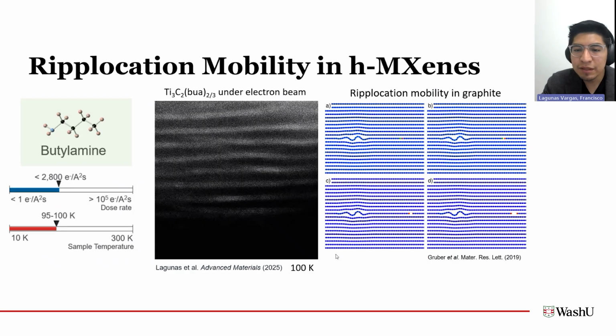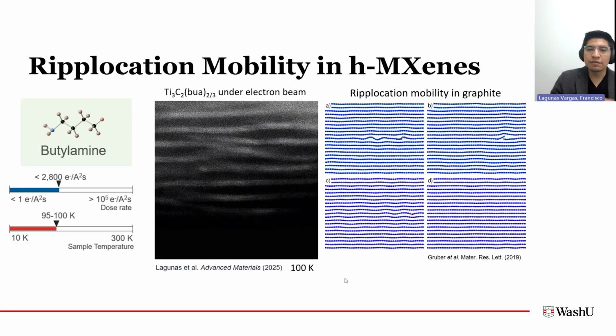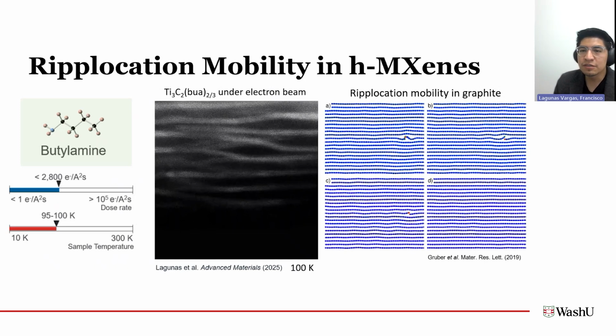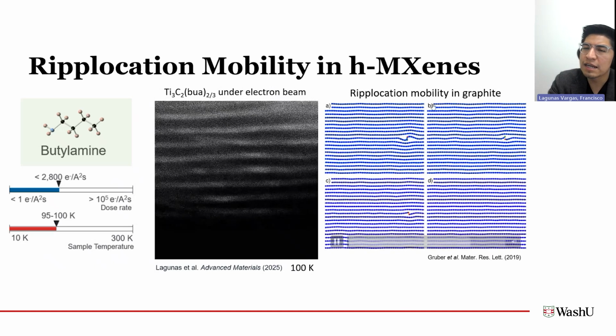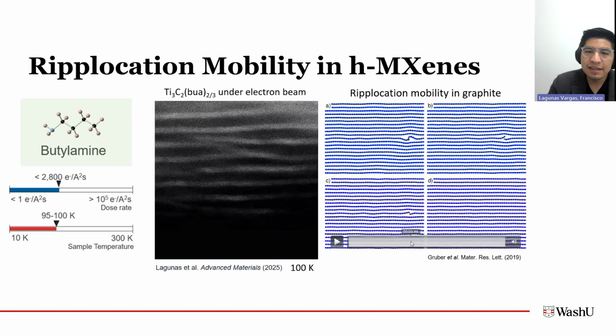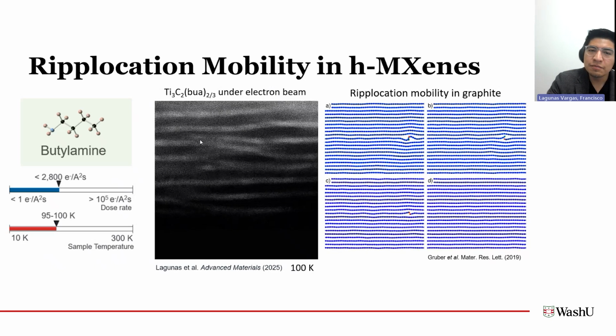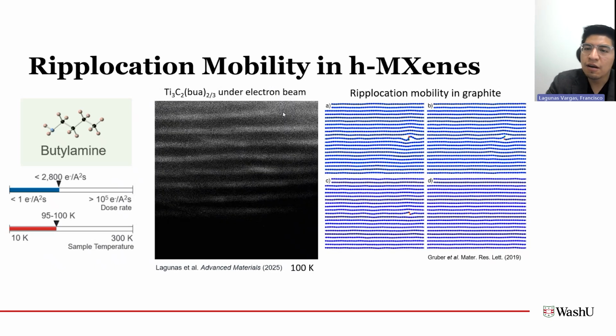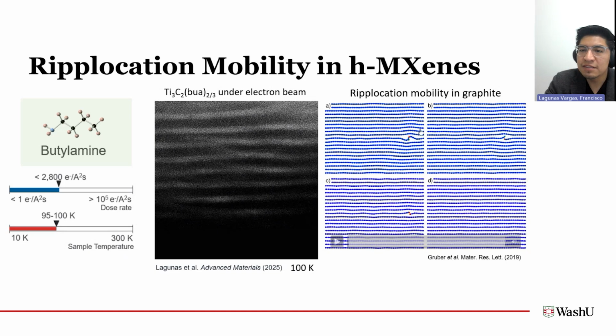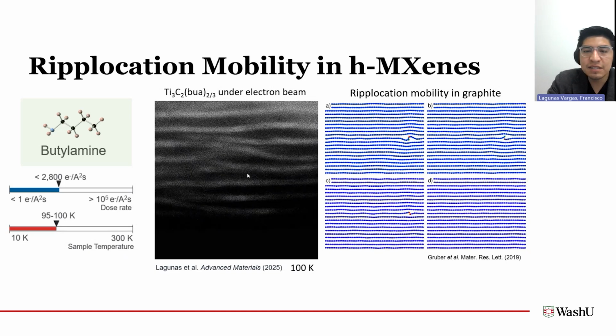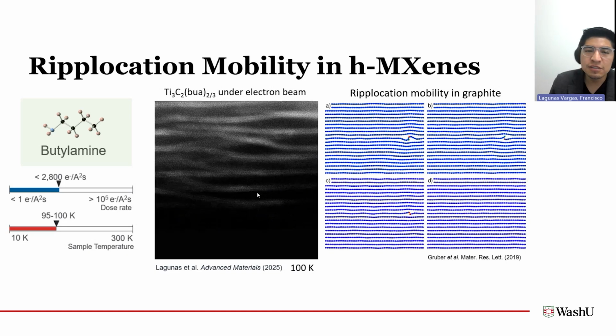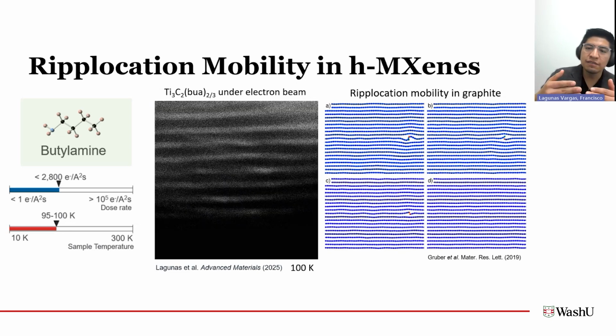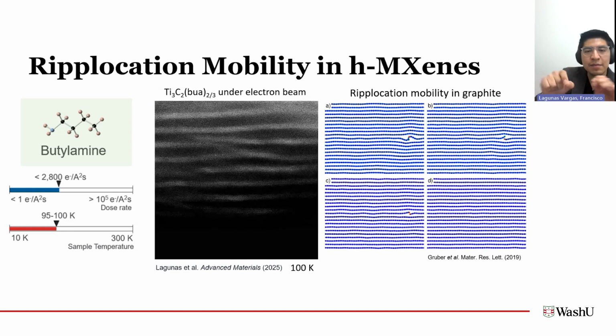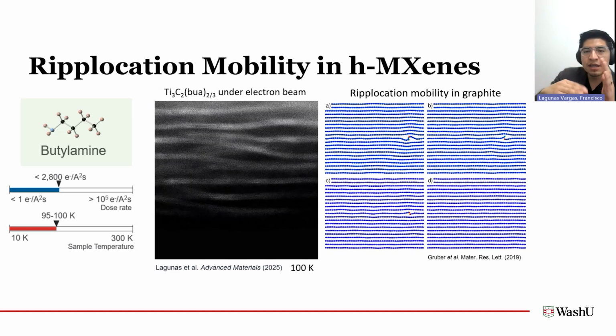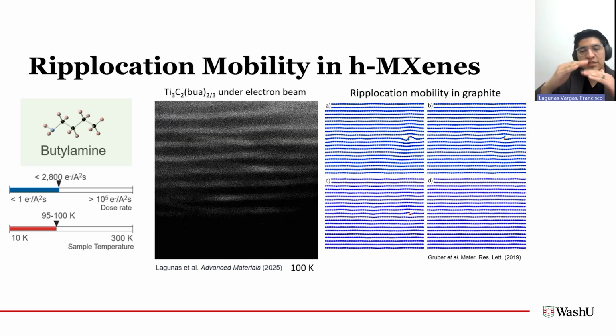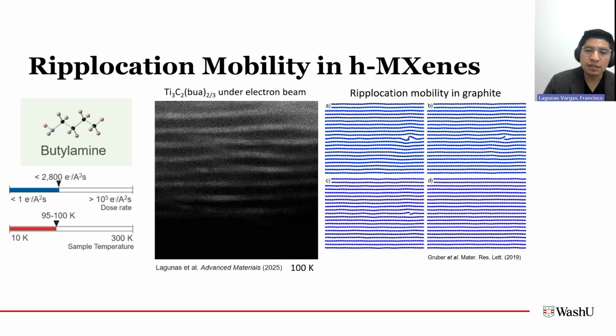So there's a lot of work where people have done computational modeling of the motion of these Ripplocations in 2D materials. Here's one where a group did a molecular dynamics simulation of Ripplocations in graphite. And you can see the movements that they observe tend to match what we see. You can also see that the effects of local vacancies in the material lead to this tearing-like effect, which is what we think is happening. So as you accumulate enough electron dosage, you're knocking out titanium atoms in addition to destroying the organic surface groups. And then you have these Ripplocations that are migrating to those defects, where you end up having this really altered structure in the end.